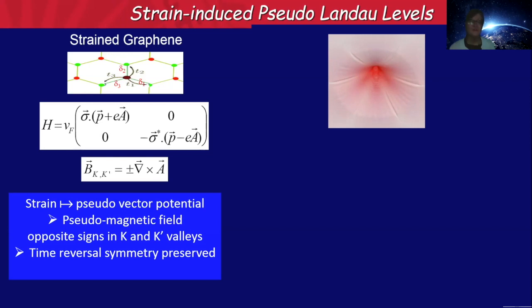However, notice that there's a big difference. Here we're not breaking time reversal symmetry. So the vector potential at the K valley has opposite sign to the vector potential in the K prime valley. In other words, we call them pseudomagnetic fields, and they have opposite signs in the two valleys. So this magnetic field points up in one valley and it points down in the other valley. So there's no net magnetic flux in this system.